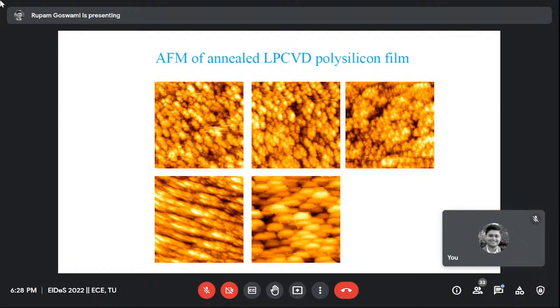If we do the polysilicon film as it is without doping, and then we do annealing, this is the change in the grain size, and this is quite stable actually. For example, elongation. If you make the piezoresistive resistor of this polysilicon film after boron doping, then perhaps the piezoresistive coefficient will be different. And this stage will be quite interesting, that we can have the desired piezoresistive coefficient by varying the grain growth, by the grain size.